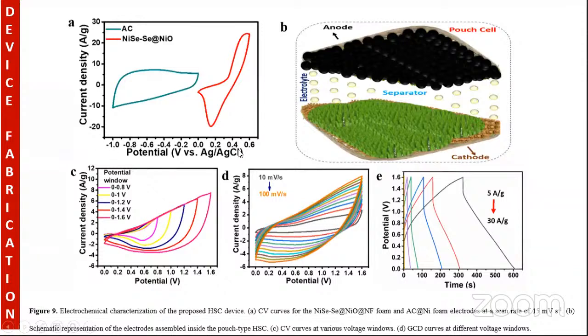Now, this is the beauty of a hybrid supercapacitor, where we were able to increase the voltage window, which directly increases the energy density of the material. Coming to figure C, we have also tested the stability of the electrode, or the device you can say, at different potential windows. We found that the device could be used from 0 to 1.6 volt.